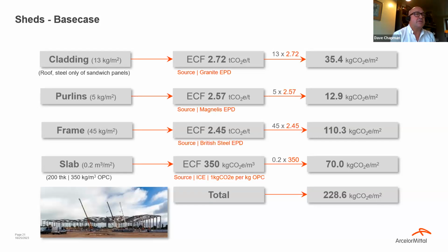That multiplies through: 13 kilograms per metre squared at 2.72 tonnes per tonne is equivalent to 35.4 kilograms of carbon per metre squared. So there's a good metric we can use there. And looking at the purlins, something similar. And of course, the frame is a big element, 45 kilograms per metre squared, reasonable. And that gives us 110 kilograms of carbon per metre squared. Totaling all those things, including the concrete slab, regular concrete, there's no GGBS in that, gives us a total for a building of 230 kilograms per metre squared.